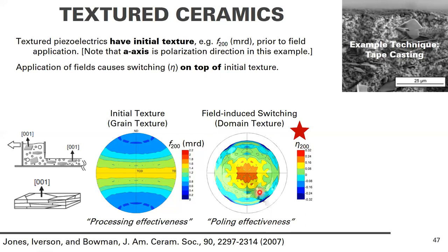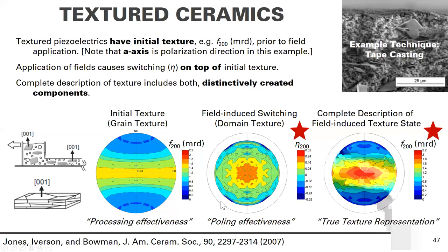Okay? Now, I described the first one as the processing effectiveness. How well does the tape casting technique produce a strong texture? And over here, the poling effectiveness. How effective is the electric field at generating switching in the sample? Okay? Now, at the end, you've oriented domains via both grain engineering and domain texturing, okay? So the complete description of field-induced texture can be shown as a third pole figure, okay? And this is the true texture representation.